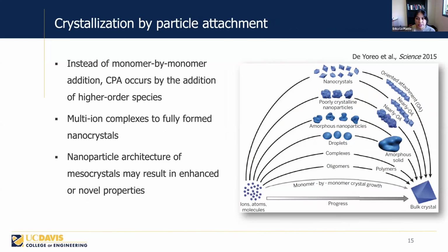So coming back to this idea of crystallization by particle attachment, this is a seminal work by De Yoreo in Science in 2015, synthesizing the findings in the community, in which we are increasingly finding evidence for this mechanism of crystallization by particle attachment. Instead of monomer by monomer addition, which is the classical mode of ions attaching to a growing nucleus, there are intermediate steps. So formation of nanocrystals or crystalline nanoparticles, amorphous nanoparticles or multi-ion complexes. And then these intermediate particles form, for example, an oriented attachment, mesocrystal or near-oriented structure and so on, that eventually evolves to form the bulk crystal.